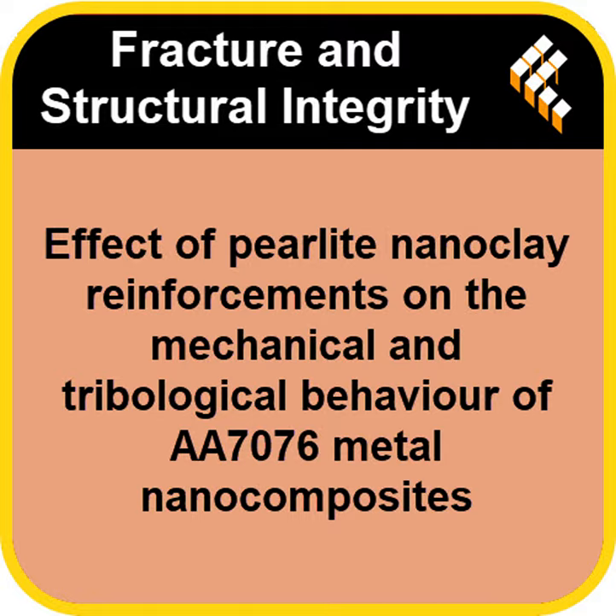Okay, but there's always a catch, isn't there? Right. We often talk about the strength-ductility trade-off. You make metal stronger, harder, usually gets more brittle. Did they lose ductility here? They did, yes. That's the typical trade-off. The maximum strain, basically how much it can stretch before snapping, decreased. It went from 12.2% in the base alloy down to 8.9% in that optimized 1.5% composite. So less stretchy. Less stretchy. But for many structural applications where ultimate strength is the absolute priority, think fixed engine mounts or something, that huge 38% strength gain is probably well worth giving up a bit of that elasticity.